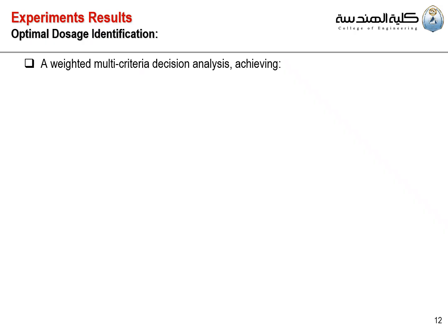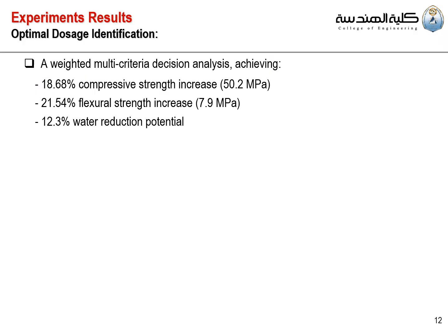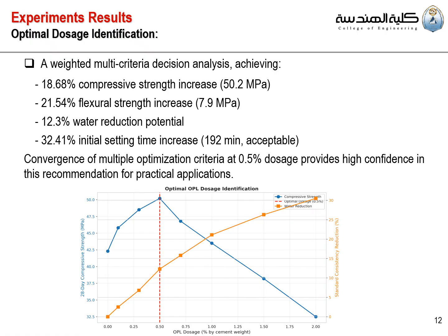So for our last research objective, we want to identify the optimal dosage level for OPL to be incorporated into the cement base and cement mortar. The study used a weighted multi-criteria decision analysis. This analysis considered the percentage increase of the compressive and flexural strength, which we already presented before. We also have the 12.3% water reduction potential and the 32.41% initial setting time increase. It is about 192 minutes. This is acceptable. The convergence of all these multiple optimization criteria leads us to the 0.5% dosage, which provides high confidence in this recommendation for practical application.